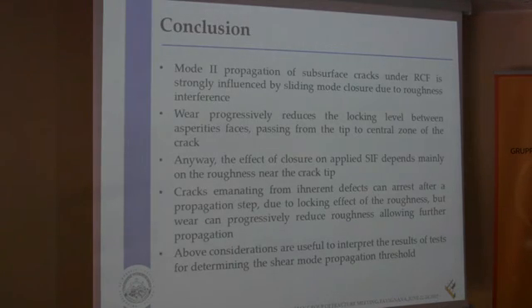So, coming to conclusions, we observed that mode 2 propagation of subsurface cracks is strongly influenced by sliding mode closure due to the roughness interference, which progressively reduces the locking level between asperity faces, passing from the tip to the central zone of the crack. Anyway, the effect of closure on applied stress intensity factors depends mainly on the roughness near the crack tip.